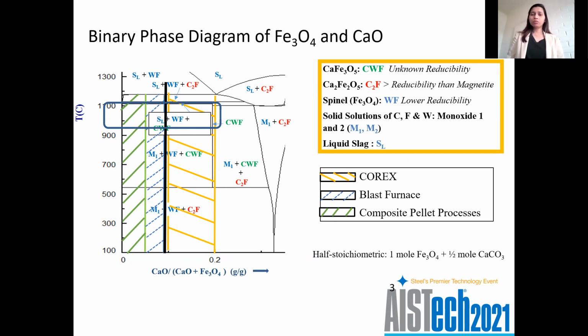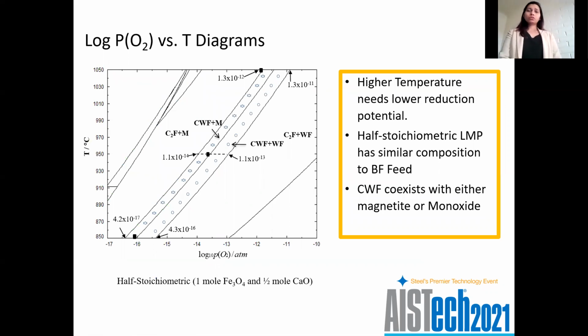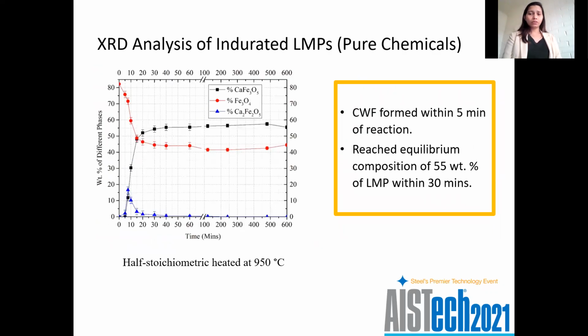Now, obviously, for our laboratory experiments, we have looked into this whole range, from stoichiometry to half stoichiometry, to see the effect of composition on the percentage of CWF. We have done experiments in the temperature range from 950 to 1050. The minimum temperature is 950 because we want to ensure complete decomposition of limestone, and you don't want to go more than 1100 because we want to avoid slag formation, as that will affect the reducibility of the LMPs. The reduction potential that we have chosen was based on the temperature and on these log pO2 versus temperature diagrams. We have also done several experiments studying the effect of reduction potential on the CWF percentage before, and these are some of the experimental results that I'd like to discuss today.